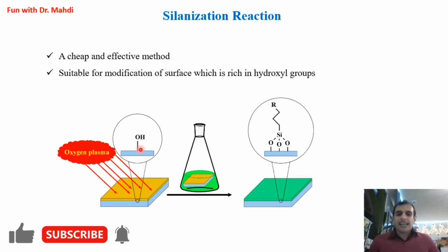Here you can see a general schematic of silanization. Again, you need to have hydroxyl on the surface. I mean, first you need to use oxygen plasma again for 2 minutes, and after that you will have a lot of hydroxyl on the surface. You have hydroxyl on your surface, you need to leave your surface in a solution with a desired compound, I mean with a compound containing silane group, and I think it's enough to leave it for 3 hours, and after 3 hours and after washing, now you have your compound on the surface.